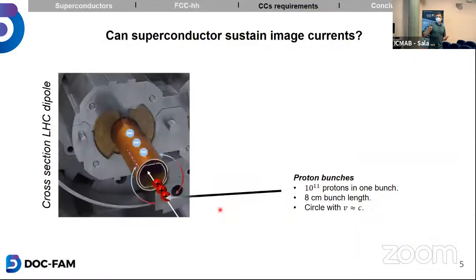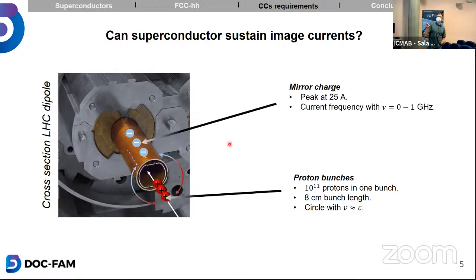And now I come to the results, so to the actual requirements that we have to test the coated conductors. One of the requirements is that it has to sustain the peak currents of 25 amps introduced by the mirror charges. As you can imagine, these proton bunches don't consist of only 3 protons. In fact, in an 8 centimeter bunch, there are 10 to the 11 protons, which circulate at almost the speed of light around the collider. And thus, the mirror charges will be quite high.